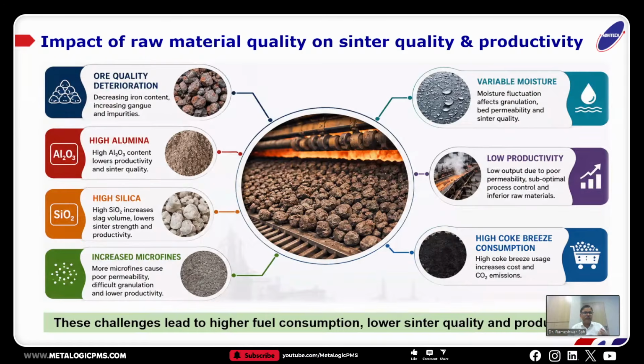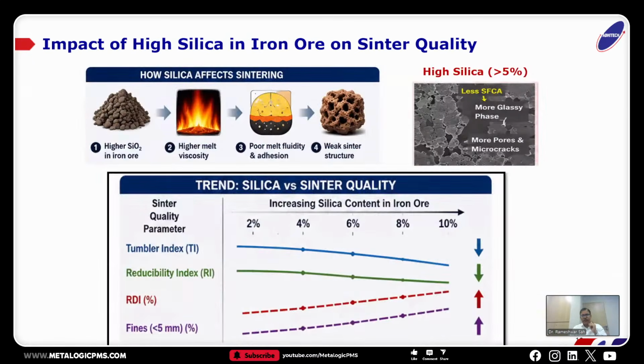If there are more gangue materials, you need more fuel. You are making more slag and less metal. So all these higher silica, alumina, alkalis, and fines are process system blocks. So how to handle that? That makes the challenge for the raw material part of sinter. Moving on, very precisely, silica. These are all undesirable things, but not absolutely undesirable. A certain amount of silica is required because it helps in making the slag phase, which is good for bonding. If the slag phase formation is not there, we will not be able to produce a good quality, stronger sinter.